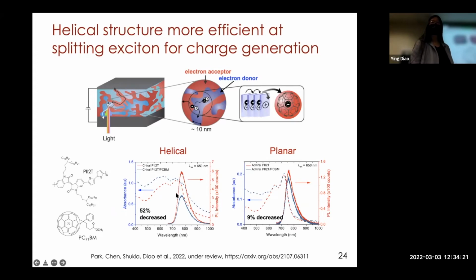Basically, I draw your attention to the solid lines here. So for the helical structure, if we blend the two materials together, that's the blue line, we can quench the recombination process of excitons, basically quench the fluorescence. This means that there are more excitons that diffuse to the boundary to split rather than recombine to emit photons. But then for the planar structure, the photoluminescence hardly changed when we blend the electron acceptor into the electron donor.